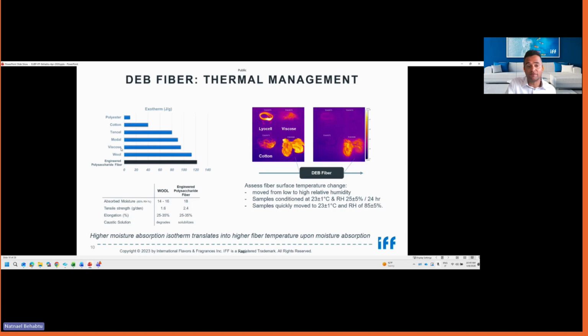Cotton is better. But we know, right, if you ask, okay, what is the high-end fiber that we wear, right, it is wool in its cashmere form, right? And the comfort associated with wool is really through this absorption and desorption exotherm. So it regulates the heat, right? It heats up when it's needed by absorbing water, and it cools down, releasing water. What you are seeing here are just IR images, so they show the temperature gradient. So the samples were conditioned at low relative humidity, and then the relative humidity was changed to high, and at high relative humidity, the material is absorbing moisture and it's heating up. And what you see, compared to lyocell, viscose, and cotton, is that this DEB fiber has thermal management, the heat up as well as the opposite, the cool down, that is even higher.